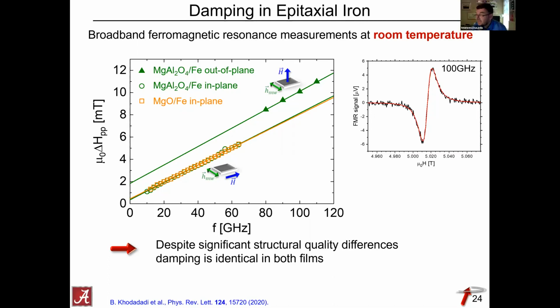Yeah, that's actually correct, and that's what I hinted to with a system with a perpendicular anisotropy. It's the same kind of argument. When you have these elliptical orbits for in-plane measurements, you're actually not as sensitive to variations of the perpendicular anisotropy as when you're measuring in the out-of-plane configuration. Whether that's the case here, I doubt it because we haven't seen any noticeable out of plane anisotropy on those films. But it is something we've seen in other material systems, that your out of plane delta H naught can be larger than in plane, or quite frequently is larger than in plane.